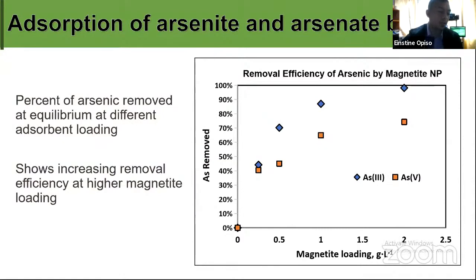So here are the results of our adsorption experiments, and they showed that our magnetite nanoparticles were able to remove arsenite up to almost 100% using a magnetite loading of 2 grams per liter. While for arsenate, the removal efficiency is only about 70%, and the adsorption shows an increasing trend with increasing magnetite loading.